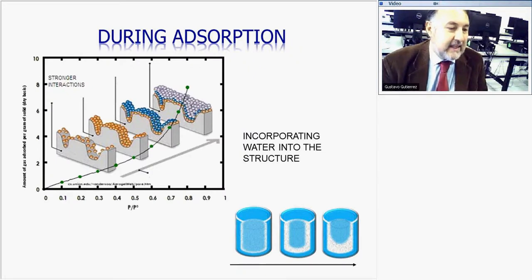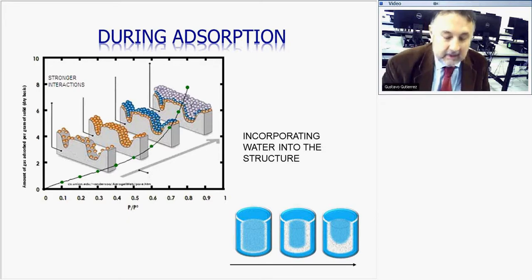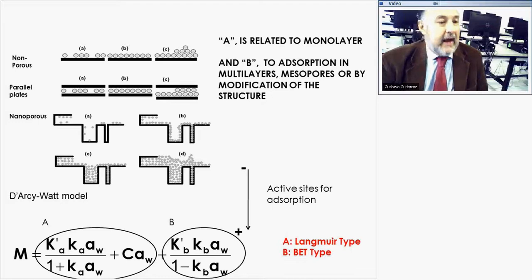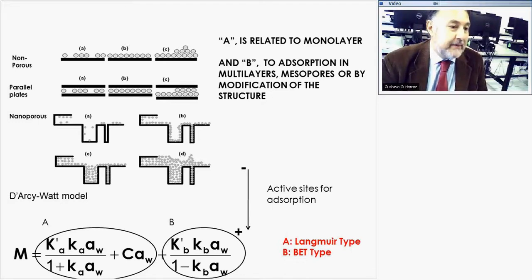The model, of course, has a typical sorption isotherm in which the first layers of water interact with high energy with the material, and then the following layers interact with less energy at higher water activity by filling the pores that we have in the microstructure of the material. And with different behaviors, we can have a non-porous material. These are related to the sorption of water, these circles here are the water molecules. We can have nanopores, or we can have a series of pores, a more complex sorption behavior.